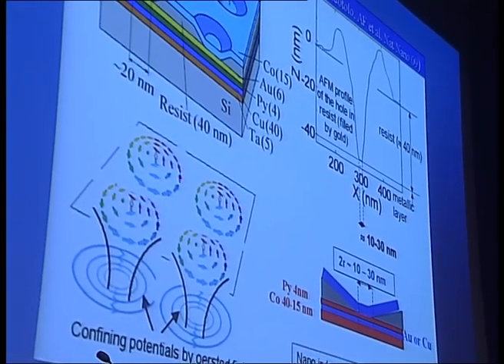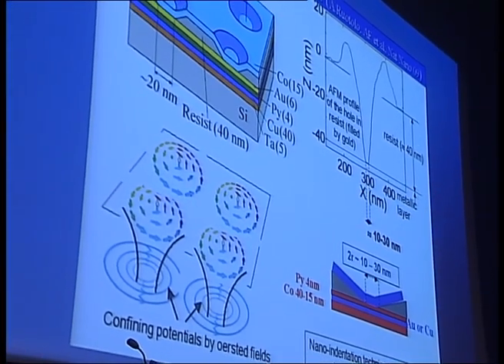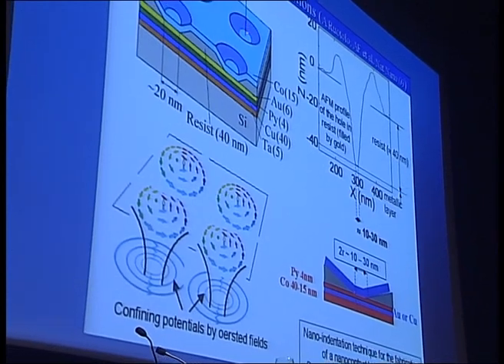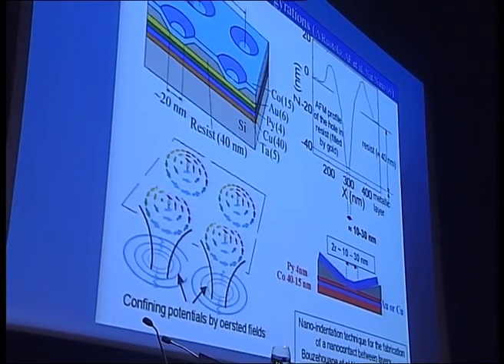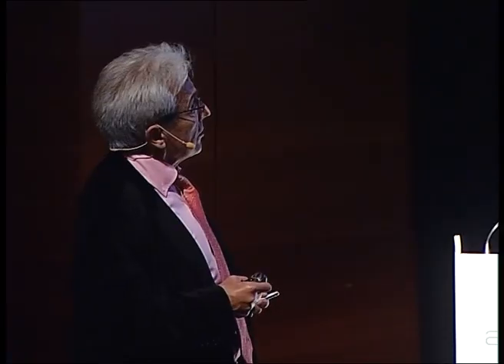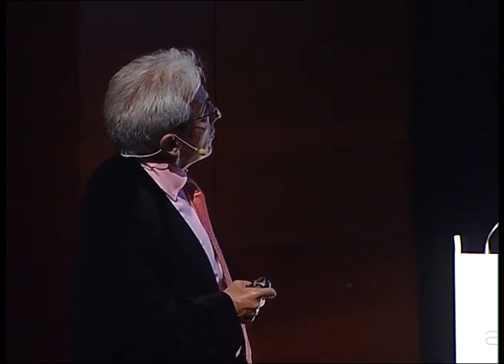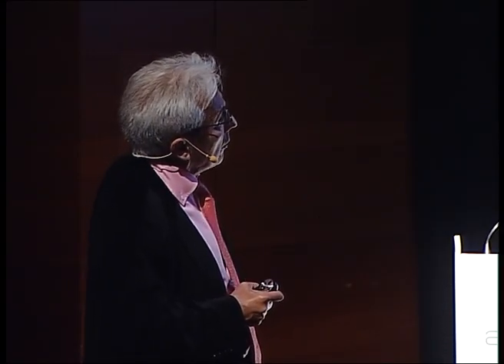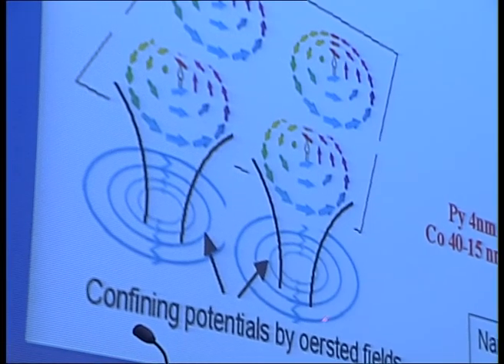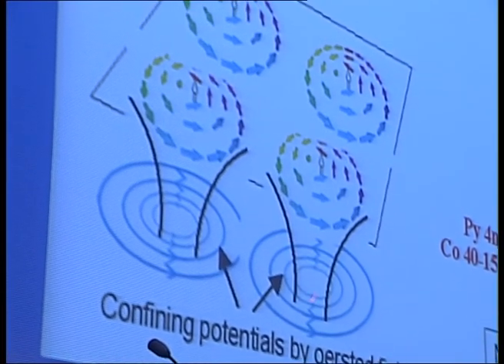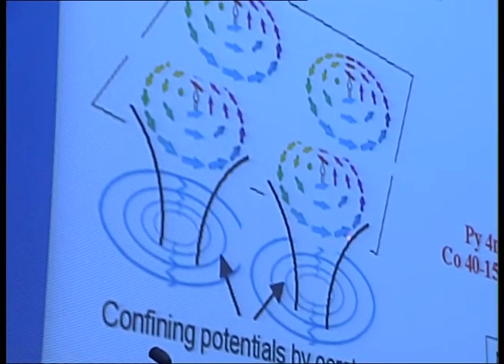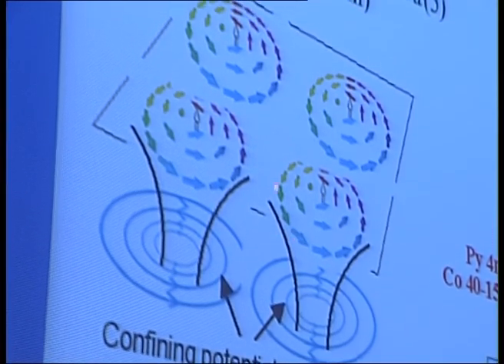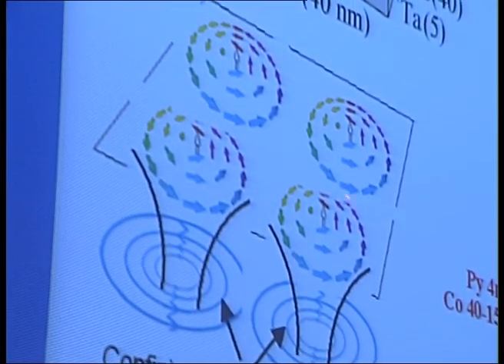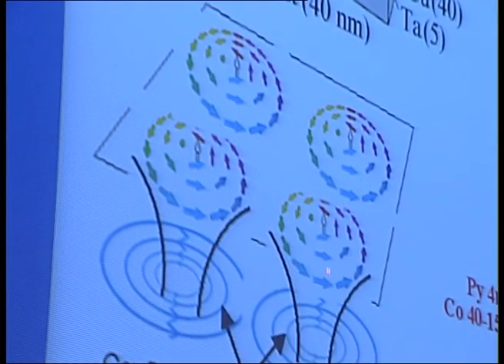In fact, we obtain this vortex also in nanocontacts by injecting a current into a tri-layer through a nanocontact. In this case, the vortex is stabilized by the Oersted field, the circular Oersted field generated by the current in the nanocontact, because now this is a low energy if you put the configuration in a vortex configuration.